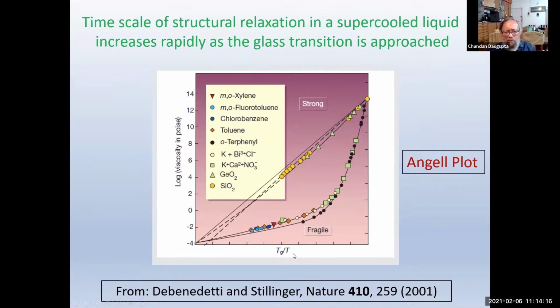And so, as you reduce T, one is going in the positive x direction. And as you can see here, the viscosity is increasing by like 10 or 12 orders of magnitude over a pretty small range of this temperature. And the growth of the viscosity, or growth of the relaxation time, has different characteristics in different systems.